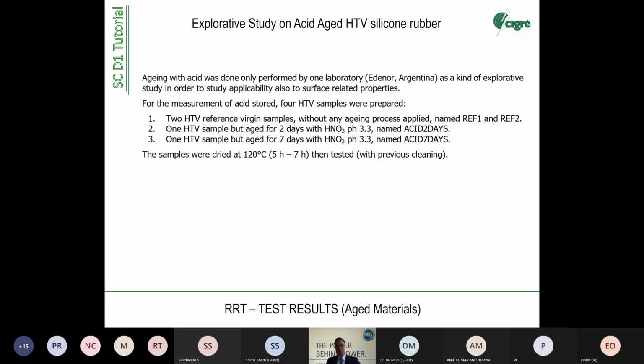Then finally, we did another one because at that time, maybe you can remember, 5-6 years ago, there was a big rush and hype regarding acid attack on polymeric materials, which occurred under certain conditions. Some people in the working group tried to steer the scope in this direction because it was very present at the time and was feared as a big hazard to the industry. So we said, okay, let's try how we can detect such acid attacks. Acid attack is mainly on the surface, by the way. When we look into acid attack on polymers, the depth is some 100 micrometers, and then it stops because it's a self-protecting layer. But okay, let's have a look at the results.